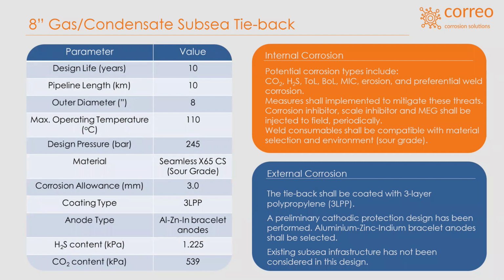So we've got measures in place to mitigate against these, such as the injection of corrosion inhibitor, scale inhibitor, and MEG to prevent hydrates into the field periodically when required, when we have more information to set up a regime on this. We'll also be making sure that the weld consumables are compatible with the material that we have selected, and ensure that it is also sour grade.